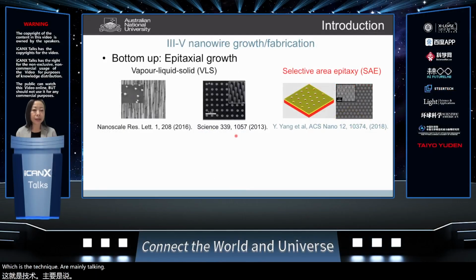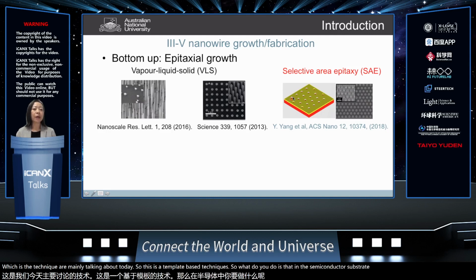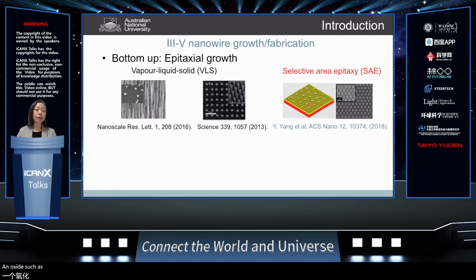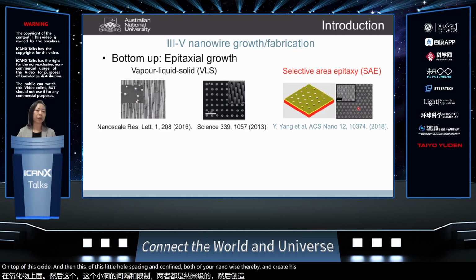mainly talking about today. So this is a template-based technique. So what you do is that in your semiconductor substrate, you can put one thin layer of oxide, such as silicon dioxide, or you can put silicon nitride, and using nanolithography technique to open holes on top of this oxide, and then these little holes basically can confine the growth of your nanowires. Thereby, you can create these beautiful nanowire arrays. So I'm going to talk about this today.